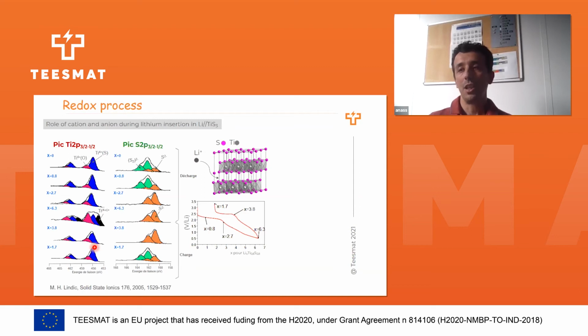When we charge, titanium is oxidized and keeps oxidizing, and the sulfur is oxidized, and we go back to our original spectrum. So that means we have a reversible redox process, and we can quantify the amount of electrons exchanged from the beginning to the end of charge. So from the XPS, we could follow the redox process through the whole galvanostatic curve, from the beginning, during the discharge and the charge.